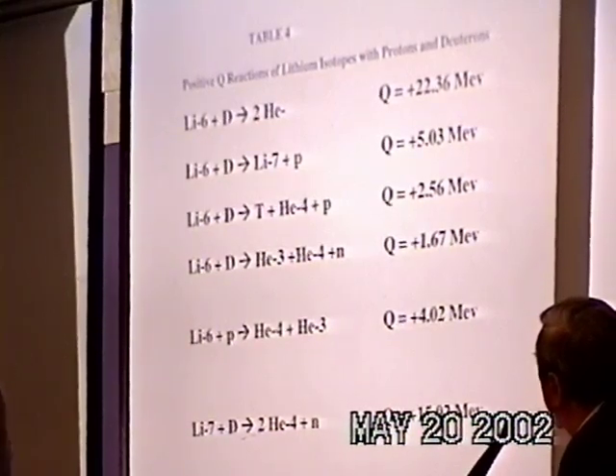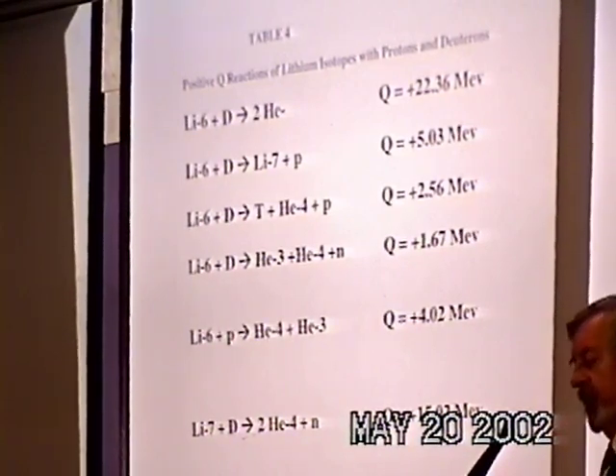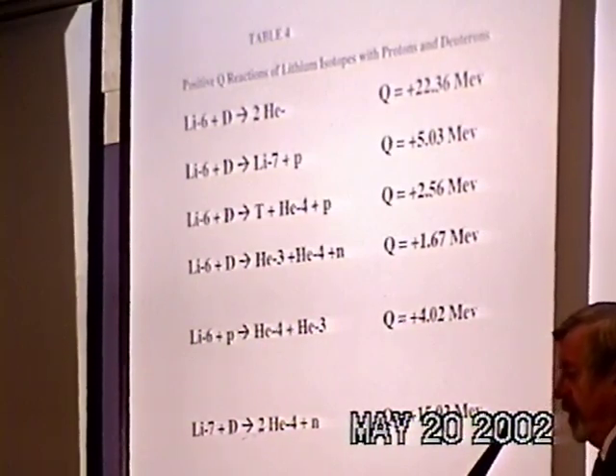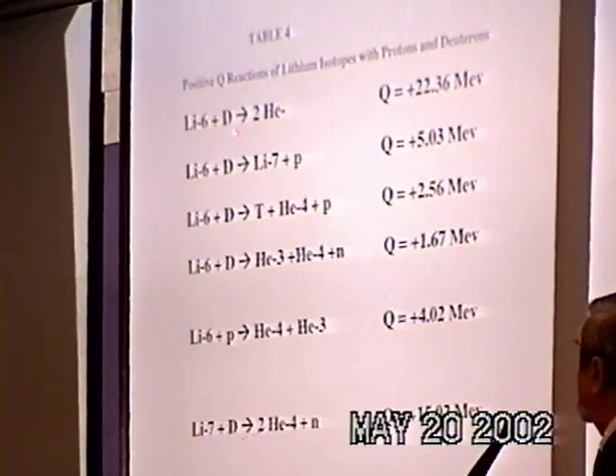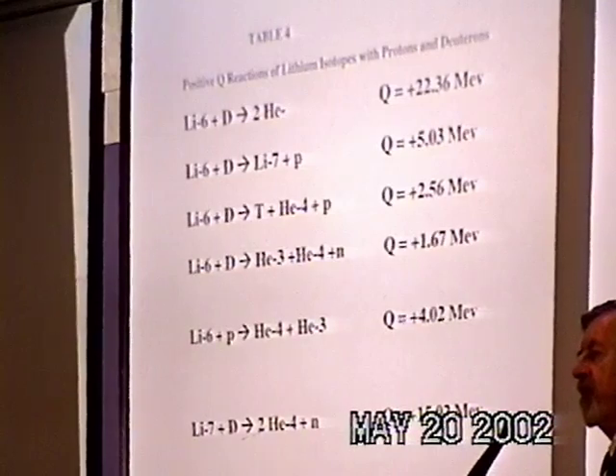Now notice I've seen 17 samples, and I've seen lithium in every one of them at the few parts per million level, which says it's a very universally present contaminant, or a tramp element, or whatever. So it isn't that we haven't always tested lithium, because it's always been present in some form. It is easy to observe, easy to measure, and there aren't many ways that you can be fooled by lithium-6 and 7 in a time-of-flight SIMS, because there aren't that many ways to make mass 6 and 7 with multiple atom ions, which is the bane of the existence of people working at the 100 atomic mass unit level.